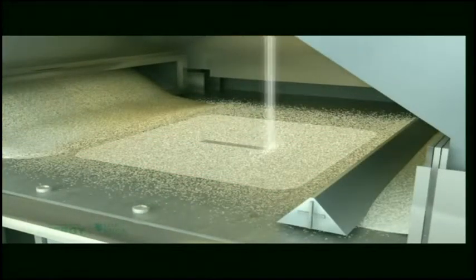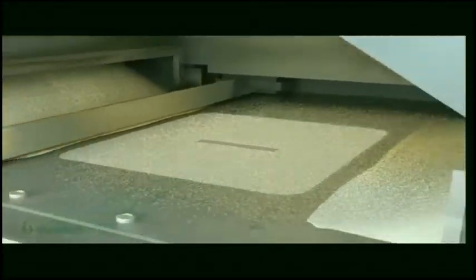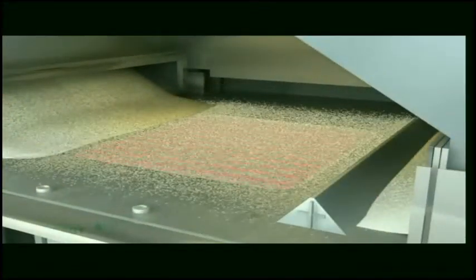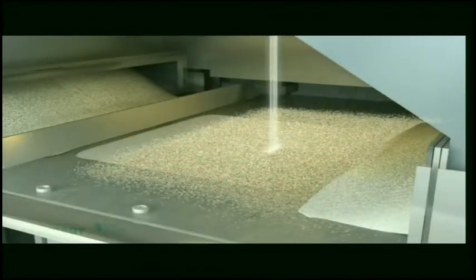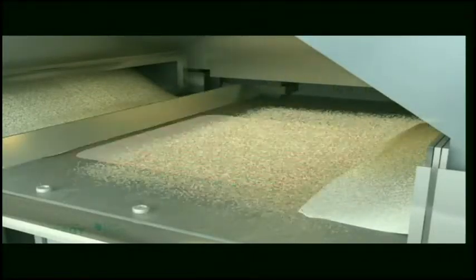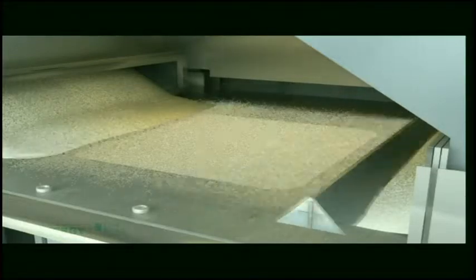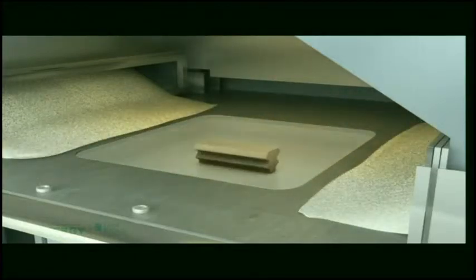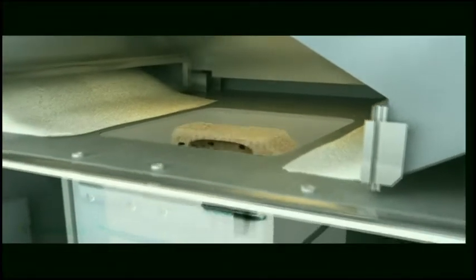That's one of the uniqueness about the electron beam technology. You can preheat each layer and then precisely come down and melt in the X and Y, the layer or the area you want to form. That process repeats itself. Now, the preheat allows us to work with some alloys that would be crack alloys and things that we would not necessarily easily be able to work with on the laser-based processes.